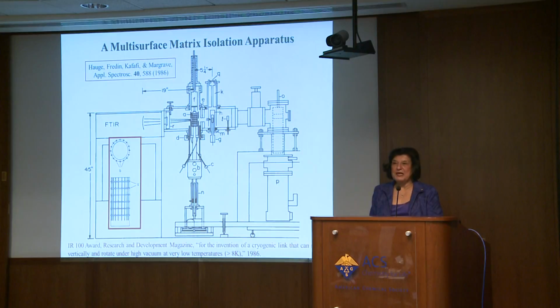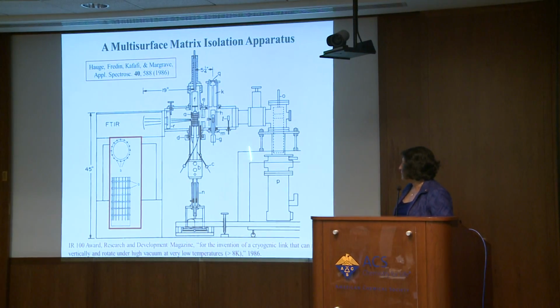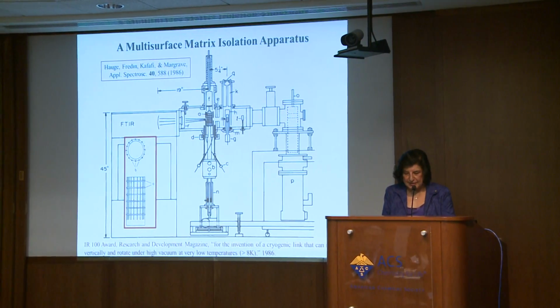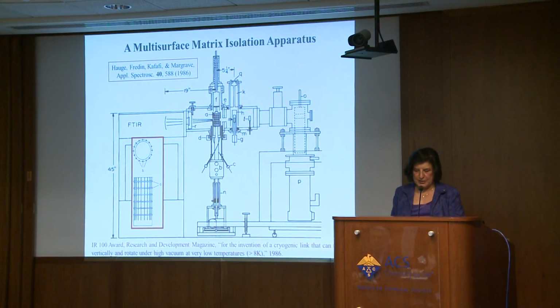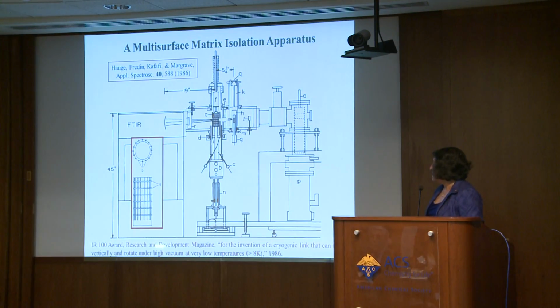So together, Bob, Leif, and I designed and built this very sophisticated matrix isolation apparatus, which is interfaced to a Fourier transform infrared spectrometer. We won the IR 100 award for a special feature that we designed in this apparatus, and I'm enlarging it here. This is the matrix surfaces. We developed a multi-surface apparatus that can translate vertically and rotate in vacuum while maintaining very cold temperature, and that's very difficult to do. This apparatus that had 5 levels was used 24 hours a day, 7 days a week by many graduate students and postdoctoral fellows.